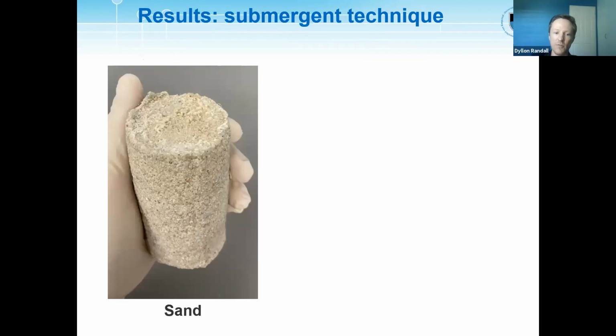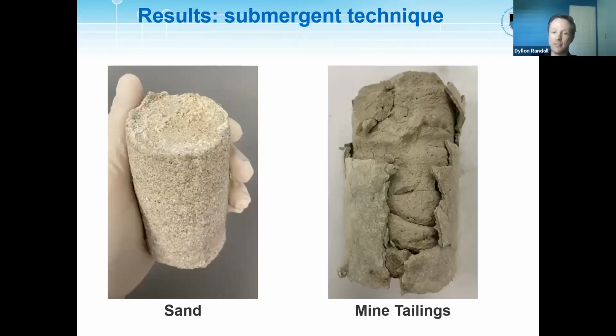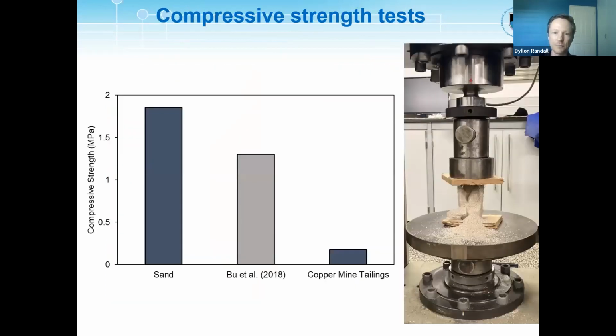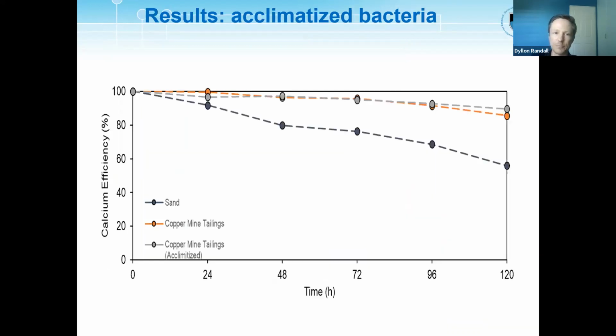So this is a column of sand being formed, and this is the mine tailings. And now there was an interesting observation, which I'm sure you can see from this, is that we had a crust forming around the mine tailings. And so when we essentially crushed the material to see how strong it was, we found that the sand compared very well, if not stronger than literature values, but the copper tailings column was substantially less. And so we thought that the main reason for this is actually the bacteria don't like a high copper concentration, and this is in fact the case.